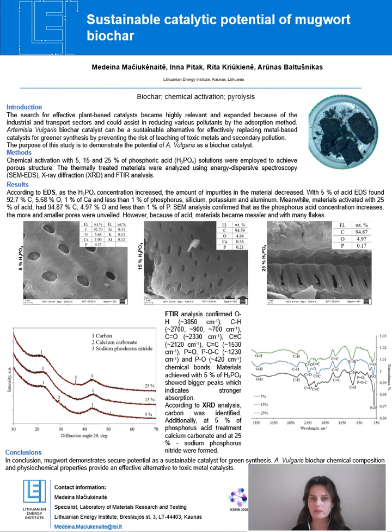Biochar possesses several beneficial characteristics such as, I mentioned, porous structure, surface functional groups, ion exchange capacity, mineral content, and relatively large surface area, and all these properties make it suitable for pollutant adsorption. Although raw biochar demonstrates promising adsorption properties, its adsorption capacity may still be lower compared to commercial activated carbon. Therefore, different physical and chemical activation methods are often applied to improve its surface characteristics and adsorption efficiency, of course.